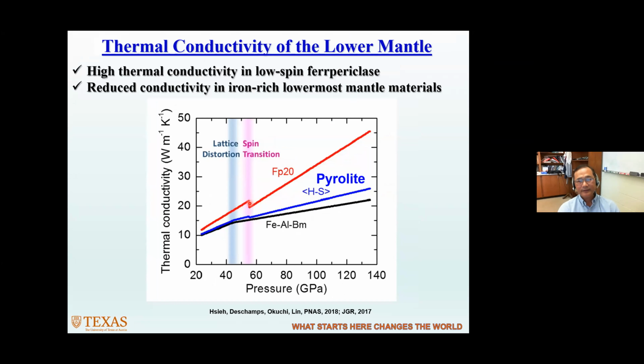Good. All right. So across the spin transition, the low spin state actually has very high thermal conductivity. On the other hand, bridgmanite, typically we think it has fairly high sound velocities, but it actually has relatively low thermal conductivity. And our explanation is that bridgmanite actually undergoes lattice distortions at high pressures that reduces its thermal conductivity. If you now put in more iron into these minerals, the thermal conductivity value decreases with increasing iron content as well.